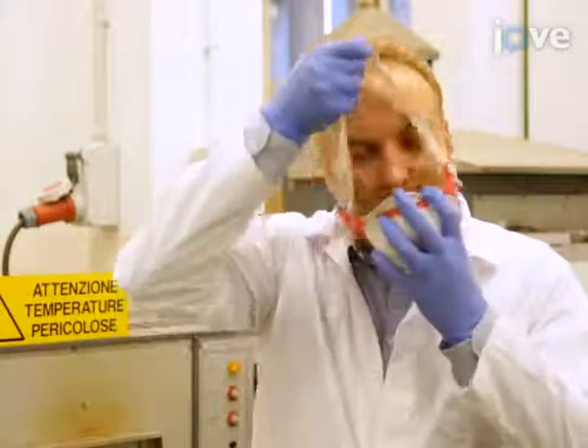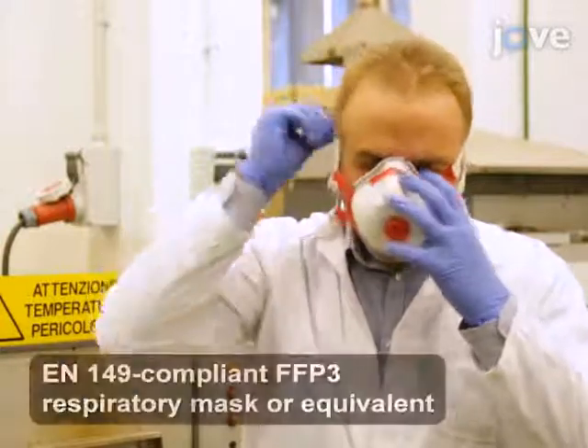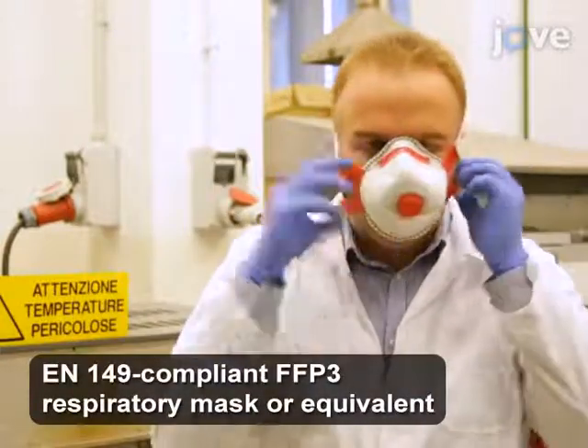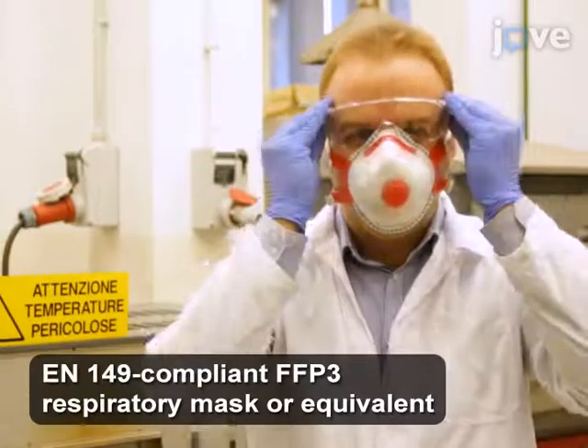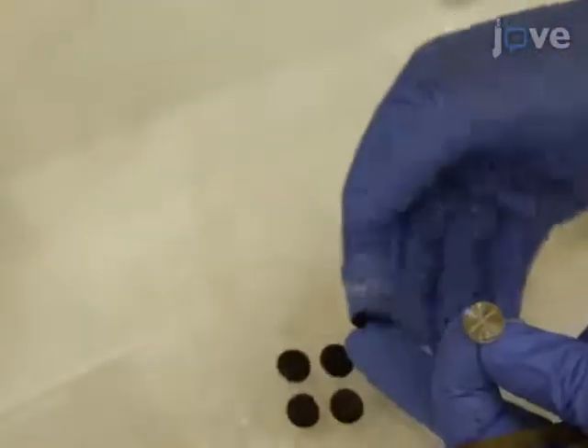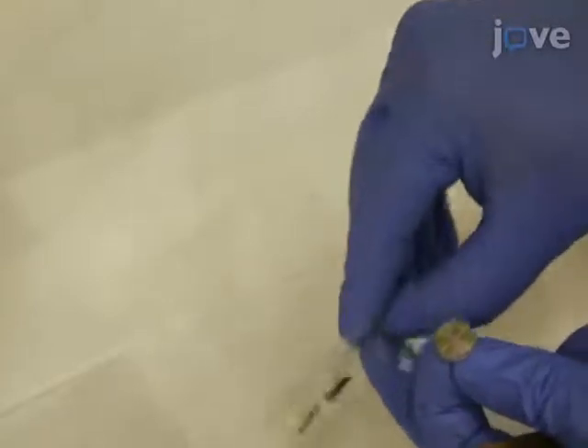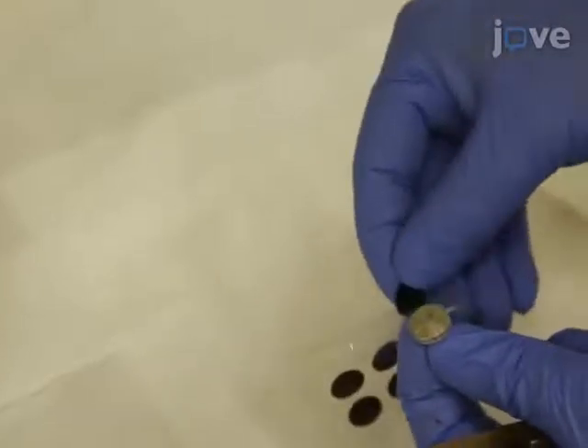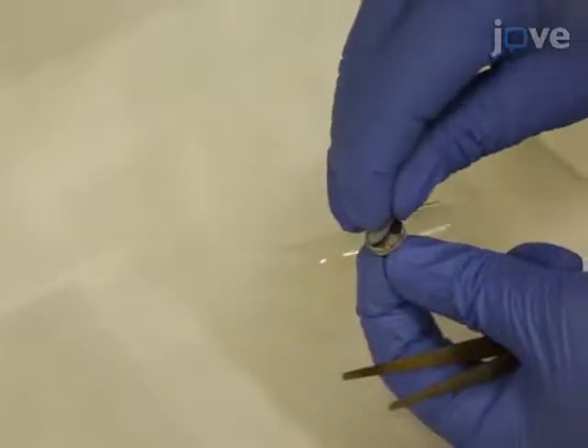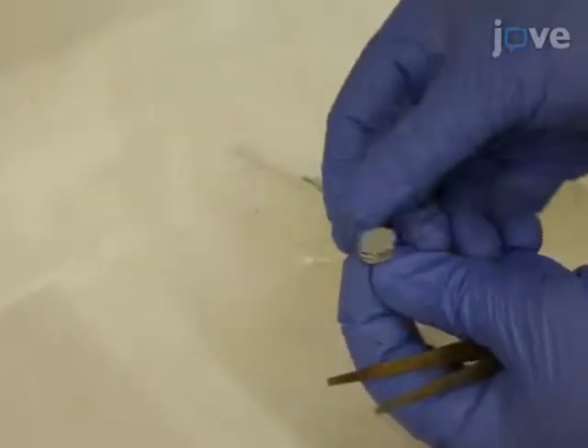When handling the titanium 6-4 powder, wear a respiratory mask, powder-free disposable nitrile gloves, and protective plastic glasses. To begin characterization of the fresh, irregular titanium 6-4 powder, fix double-sided adhesive carbon tape to an aluminum pin stub for a field emission scanning electron microscope.